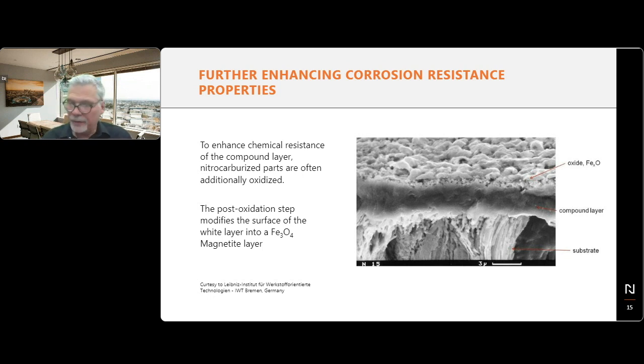So the nitrogen content in the white layer or compound layer influences both corrosion resistance and mechanical properties. The very top layer, or the epsilon, enhances corrosion resistance, and the gamma prime, which is just underlying, will improve mechanical properties. The very surface of the white layer, and you can see this in the form of small bubbles here, is an oxide, FeXO, which is mostly Fe3O4, magnetite. And this is a transformed layer. It is an oxide, but contrary to rust or what we know as hematite, magnetite is extremely compact and prevents corrosion.